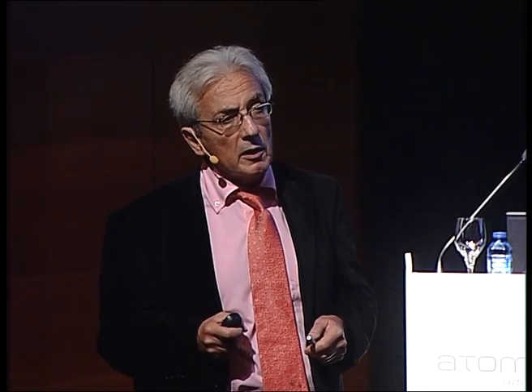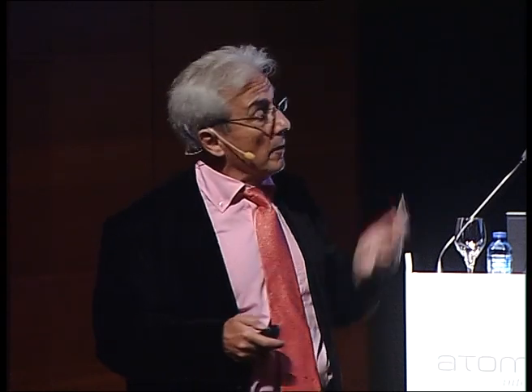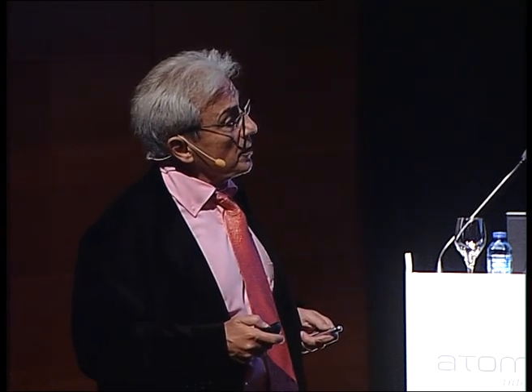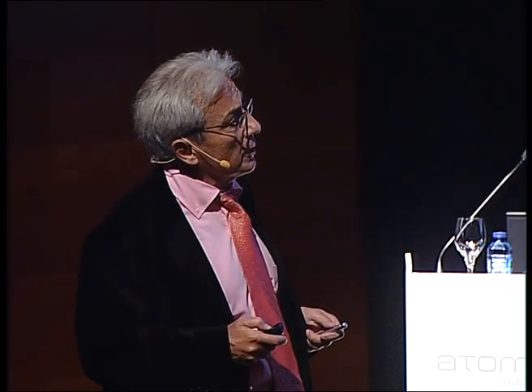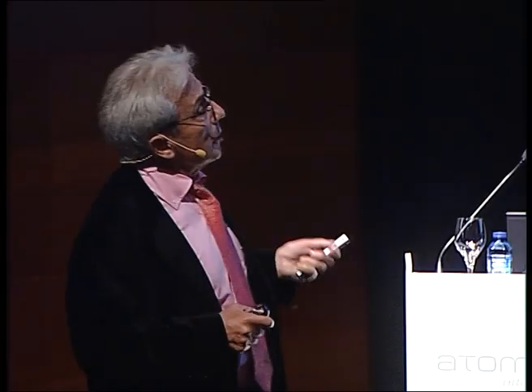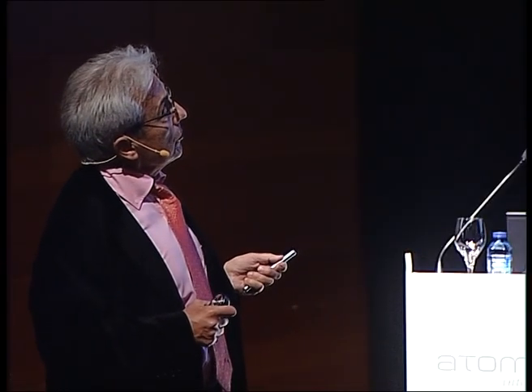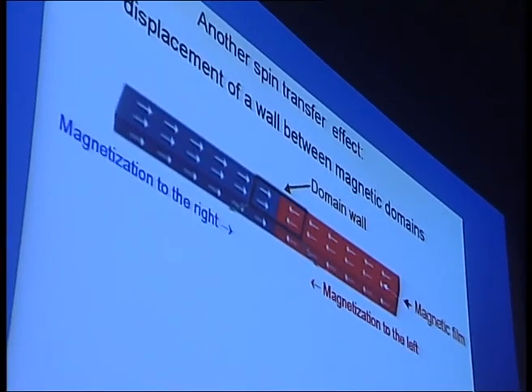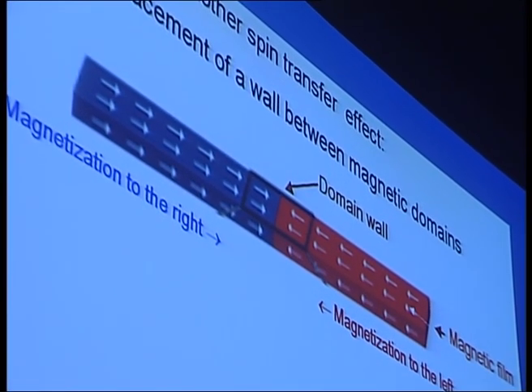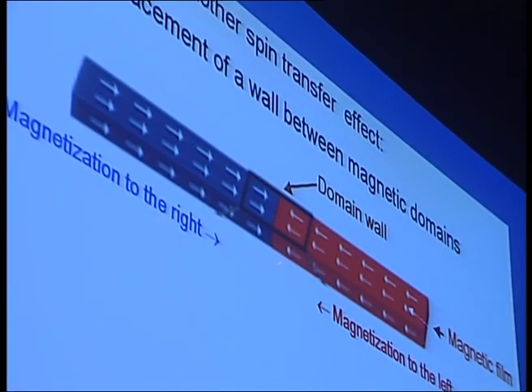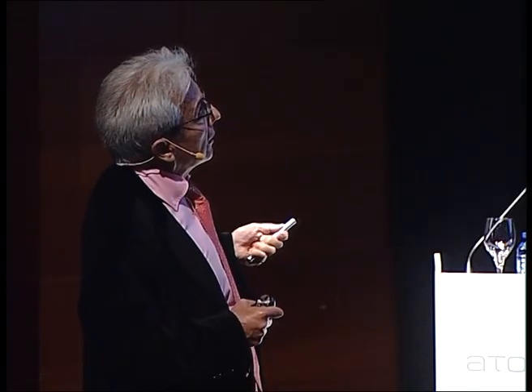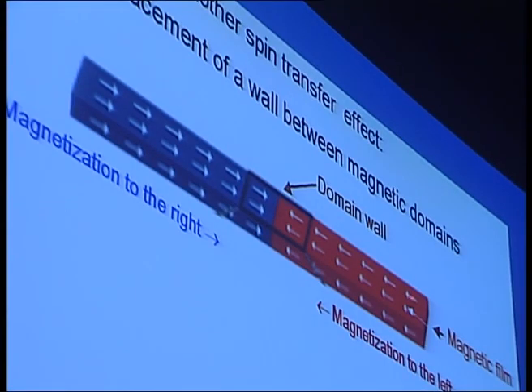You will see that we can do many things with the magnetization. And with this spin transfer effect, it's really possible to manipulate the magnetization of a magnet in very different ways. I will mention another manipulation which possibly can have also interesting application. So this is a nanowire, a magnetic nanowire with magnetization pointing to the left and to the right in the red and blue parts of the sample. In between, there is what is called a domain wall. And one of the effects of spin transfer is the possibility also of pushing and moving the domain wall by sending an electrical current. So it's motion of a domain wall by an electrical current.